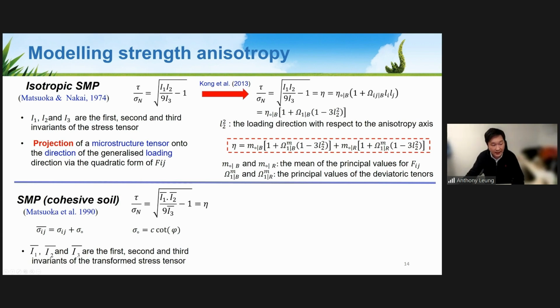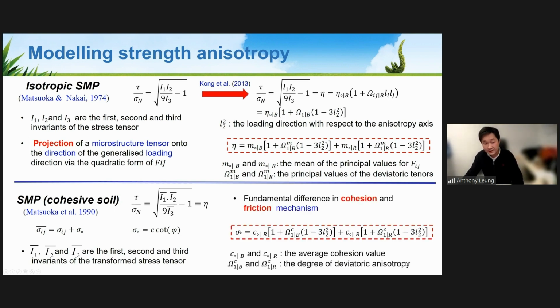So that's why we further expanded the formulation using the Matsuoka et al. 1990s model, considering cohesive soil. So you can see the mathematical form is quite similar. Actually, it's just a transformed stress tensor so that mathematically it is the same, but we have an additional term called bonding stress to capture the cohesion effect. Okay, so we then again modify this bonding stress by taking into account the root effect on the anisotropy of the soil. So these two red equations over there are the new development considering the root effect on the isotropic consideration of the soil microstructure, but also the anisotropy from the root network for the bonding stress. So now we have the mathematical model to describe the anisotropy of rooted soils.